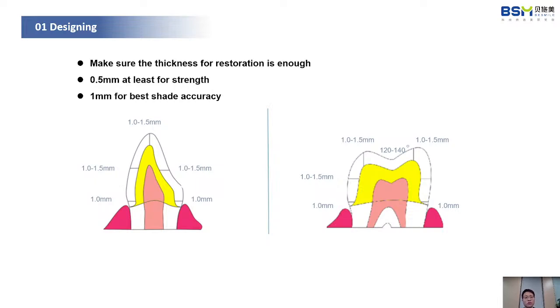So for that kind of cases, we need to make sure there are at least 0.5 millimeters. It's for the strength requirement. If the thickness is less than 0.5 millimeters, the strength will not be enough. Even though we say for our HT Plus the strength is more than 1,400 MPa, if the thickness is only 0.2 or 0.3, the flexural strength will be much lower than that number. So for the crown restoration, the minimal thickness is at least 0.5 millimeters for the strength.